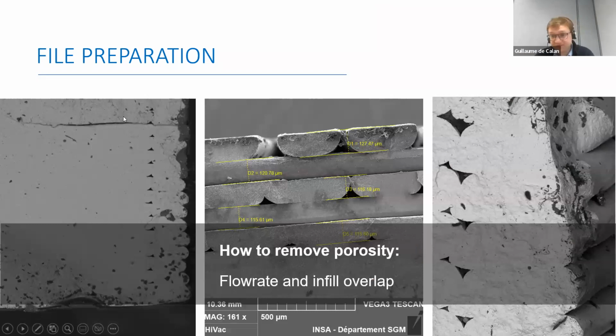The last thing also is you may have porosity in your print, and that's something very typical of FDM, FFF prints. We usually see that kind of defects if you're not printing dense enough. Here on the center part, you can see a part that has clearly been under extruded, so there's not enough material, to make it simple. So that can be corrected with some setups on flow rate. This one is clearly under extruded, so we should increase the flow rate. Flow rate is usually for our material more than 100%, 105, sometimes 110%, to make sure you're fully dense. Of course, that's very important for the mechanical strength of the part.